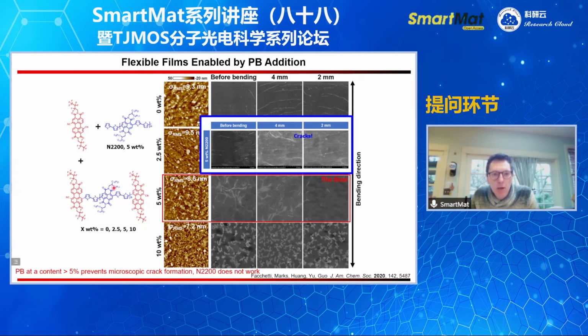And the proof is really this experiment. We have this polymer with the end group, and if we bend it, there is no crack. Instead, if we blend the small molecule with N2200, which does not have the red small molecule at the end, then you bend and it cracks. So really this polymer works through a sort of molecular recognition mechanism. And we also made polymers, this is very recent work, where the blue component doesn't have to be N2200. It can be any polymer. It can also be an insulating polymer, as a matter of fact. You still get the same results in terms of plasticization.